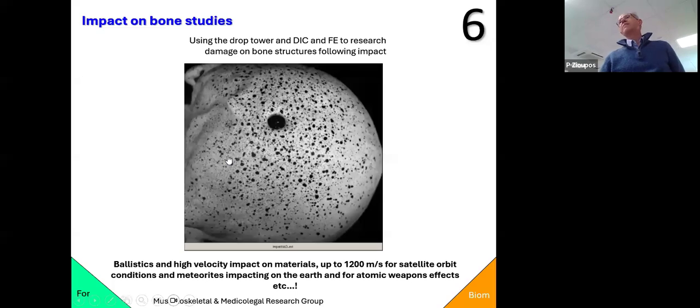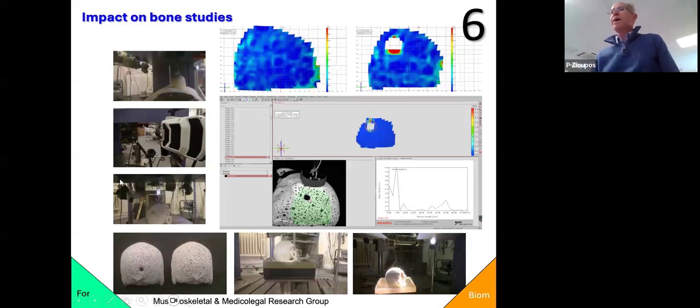So basically, it's been impacted at high strain rate to see how the skull behaves when it has a stress concentrating effect. Basically, this hole here is a defect, which can be a result of, let's say, a tumor or surgical intervention. How would this skull behave? We need to know that. So that's what you combine here: a mechanical setting where you have a 3D printed skull and a high strain rate loading. There are two skulls here, one with a defect and one without a defect, identical, recorded with high speed videos, producing the strain map on the same model.